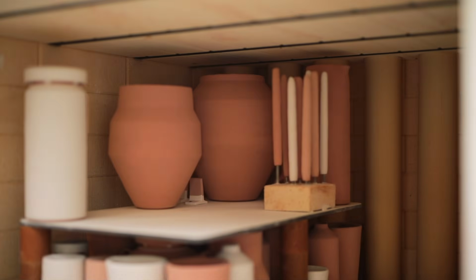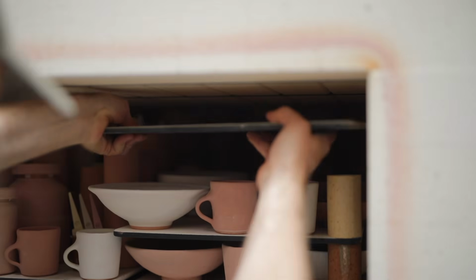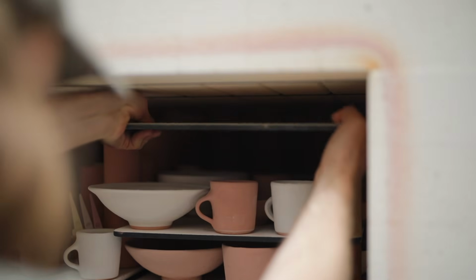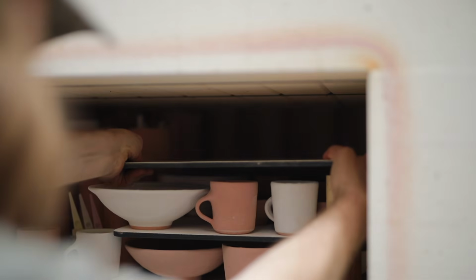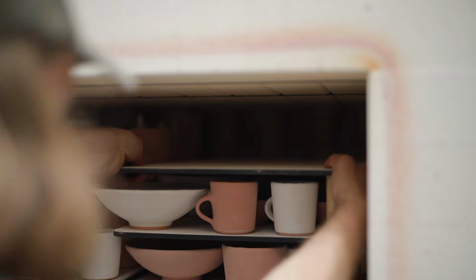Firing using gas provides you with a whole new range of colours which just aren't quite achievable in an electric kiln. For instance, the same pink glazes you see here in this kiln will fire to deep, dark greens. That's because they're fired in what's called a reduction atmosphere, which I'll go over in greater detail in a moment. But if these same pots were fired in an oxidized atmosphere, like found in an electric kiln, they'd fire into mixed yellow hues that are mottled and not particularly nice.